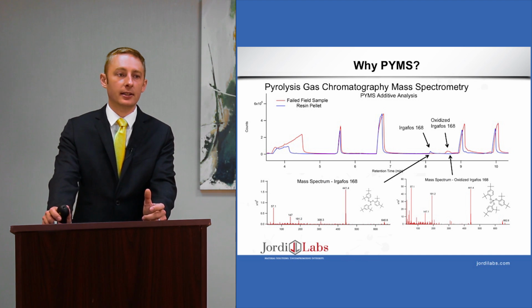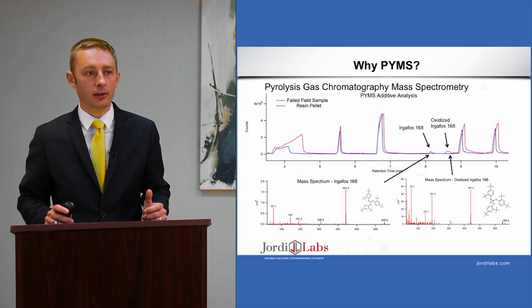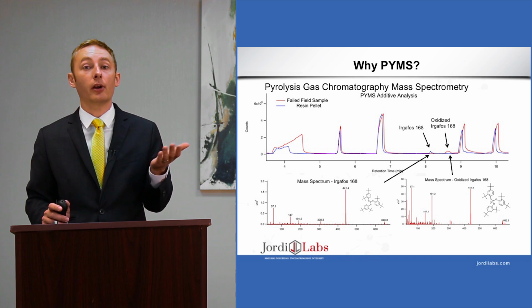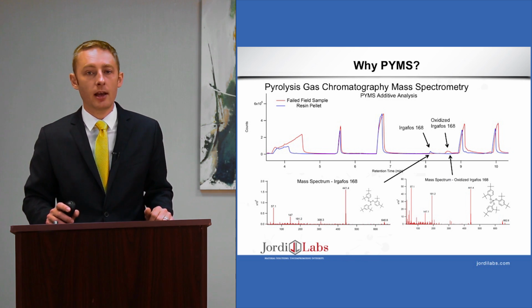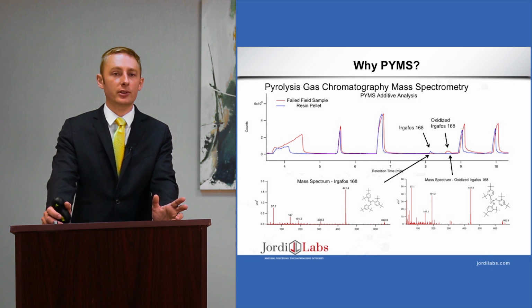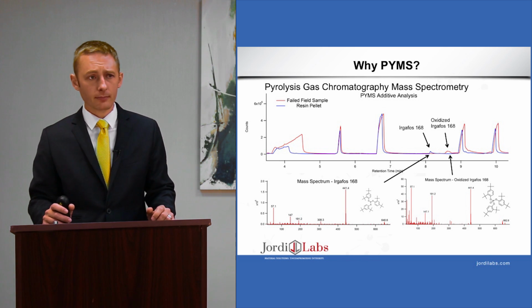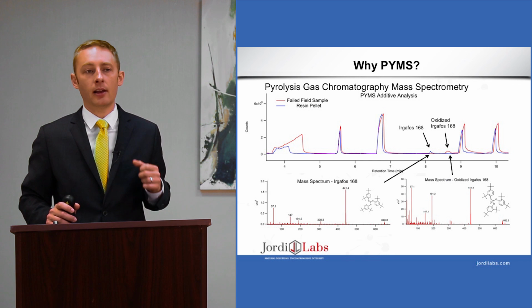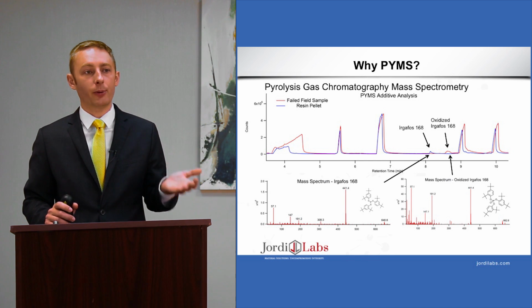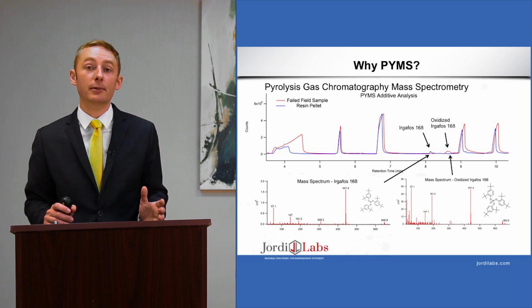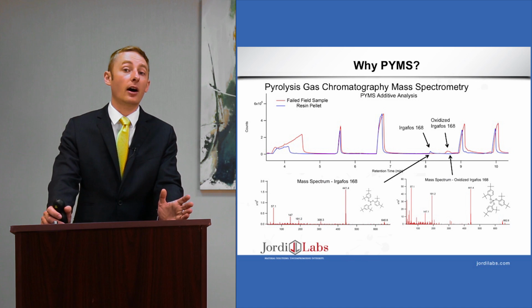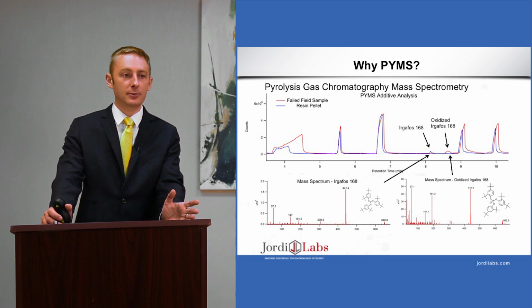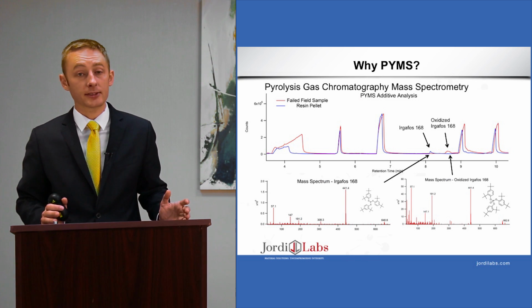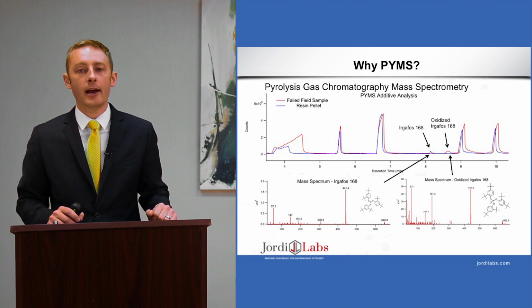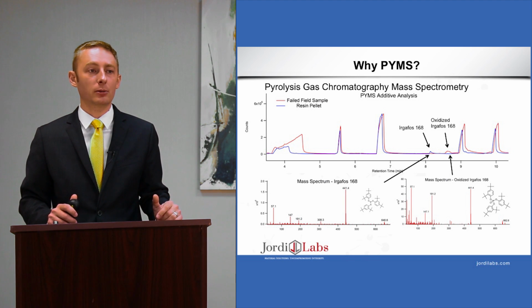So this is a technique, if you're looking at the slides right now, where, for example, we can compare a good and a bad resin pellet. And we need a very small amount for this, maybe 1 milligram of sample. And we're able to identify, for example, in the good pellet, the presence of Irgafos 168, and in the bad pellet, the presence of oxidized Irgafos 168 and the absence of unoxidized Irgafos 168. And so it's a very powerful technique for polymer analysis.